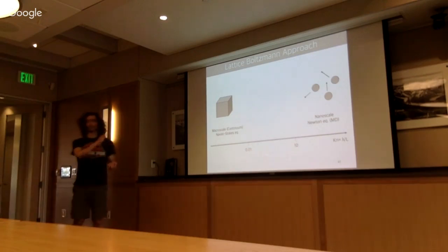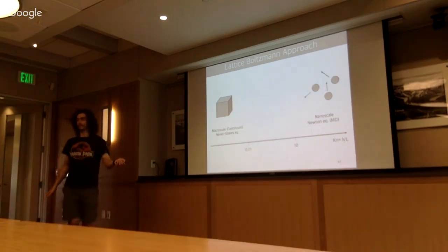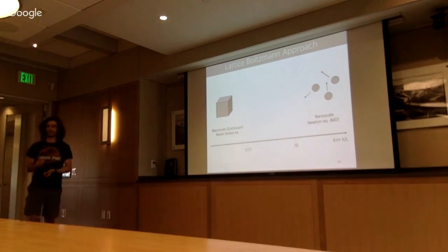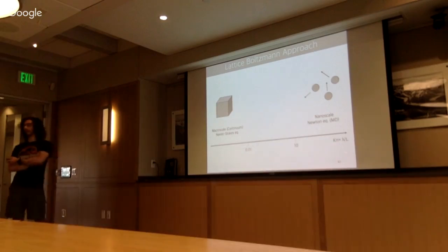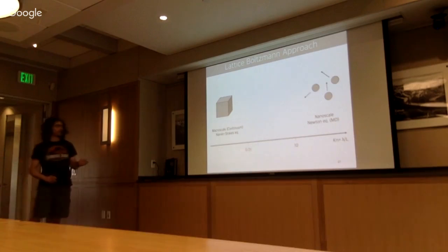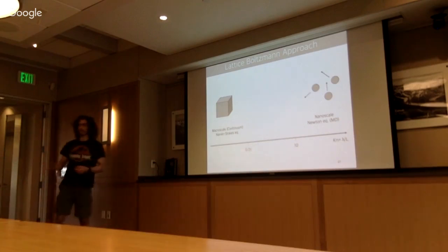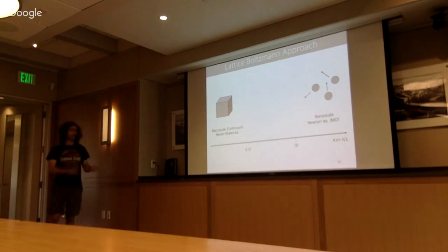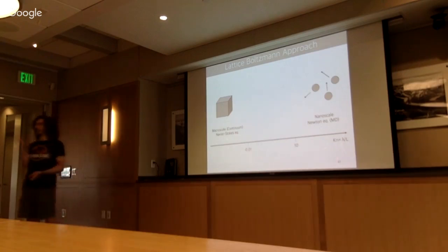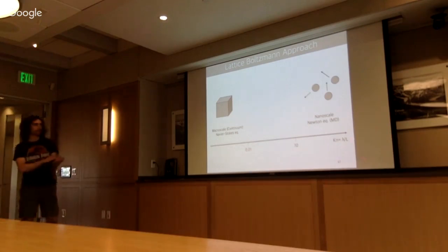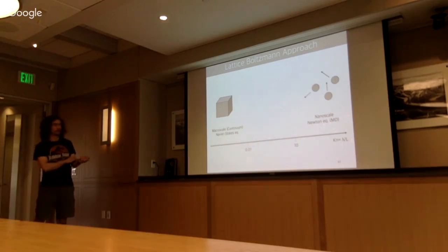When you can use one approach compared to the other is defined by the Knudsen number, which is the mean free path lambda divided by the characteristic length. In a macroscale example, for instance a pipe, L is pretty big, so the Knudsen number is really small and you can use continuum approaches. Whereas when the dimensions are really small, you better use a molecular dynamics approach. Hypothetically, you can push this one towards the macroscale, but then you have an issue with computational power.